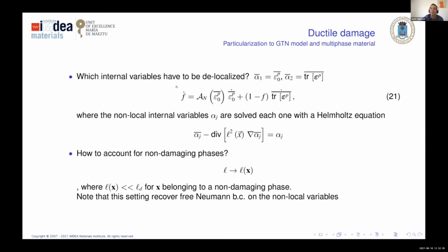So in this case, the evolution of porosity depends on the non-local counterparts of these internal variables. Okay, good. So we have to solve a Helmholtz equation for each of them. And the second question is how we account for materials where we have non-damaging phases. So in this case, we can introduce a characteristic length that depends on the position.